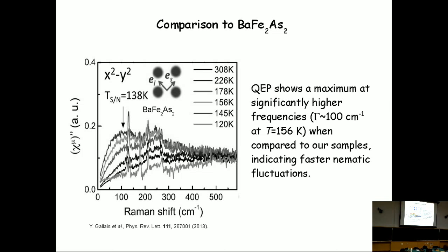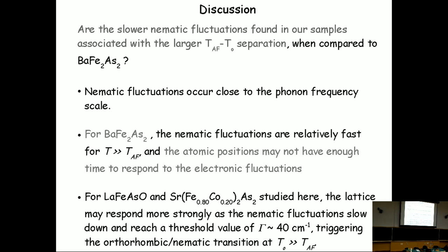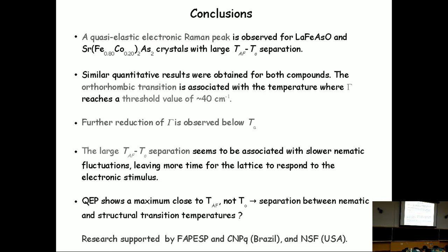So this undoped system does show nematic fluctuations, but they are quicker, they're faster than the samples that we studied. And then the question is, what's going on? Nematic fluctuations apparently are slower for the samples that we studied, which shows a separation between the two temperatures. And apparently what's going on is that when the nematic fluctuations get slower, they get to the scale of the phonons. When these electronic fluctuations get into the time scale of the phonons, the crystal lattice gets more responsive to the electronic fluctuations. And we believe that this factor is making the orthorhombic phase transition and the magnetic phase transition separate more because of these slower electronic fluctuations, which are pushing the lattice fluctuations with them. So that's pretty much what we conclude here.